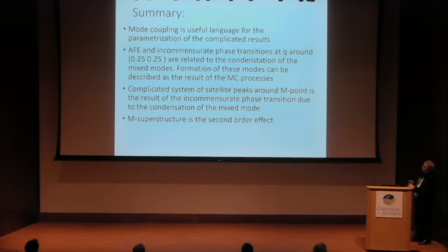And the summary is: I want to say that mode coupling is useful language for parameterization, because what I've been speaking about is parameterization, not a theory. The antiferroelectric and incommensurate phase transition at Q around the sigma point are related to the condensation of the mixed mode. Formation of these modes can be described as a result of a mode coupling process. And the complicated system of satellite peaks around the M-point is a result of the incommensurate phase transition due to condensation of the mixed mode. The M-superstructure is the second order effect. Thank you. Okay, thank you very much.